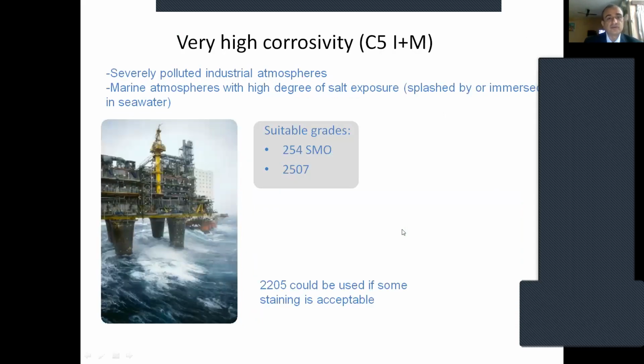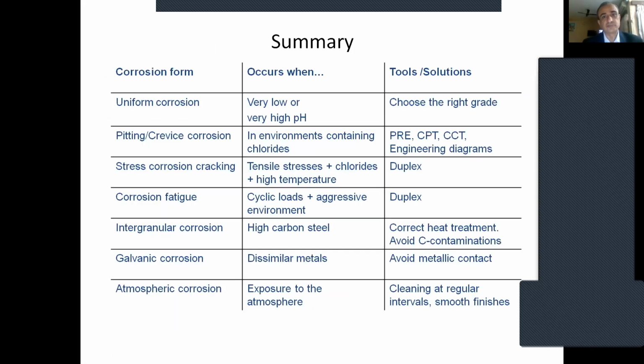It's high corrosivity, again an offshore application, like the oil rigs where oil comes out from the sea. Here again the grades are 2507 or 254 SMO, another high grade stainless steel with PRE, pitting resistance equivalent number, higher than 42, 43. That is used where high corrosivity is there, marine atmosphere and high degree of salt exposure.